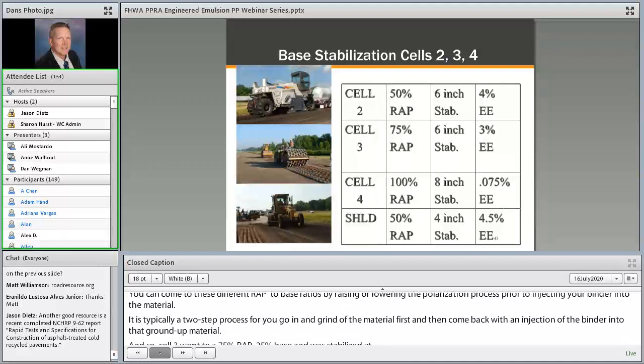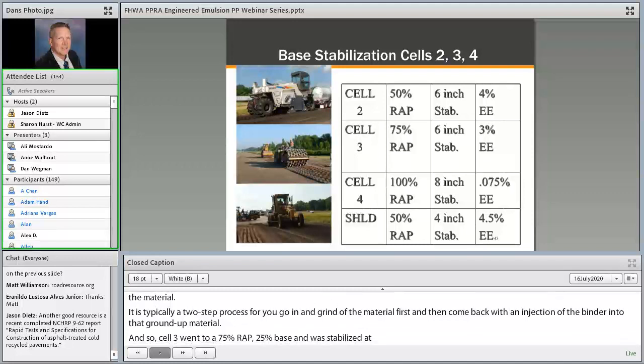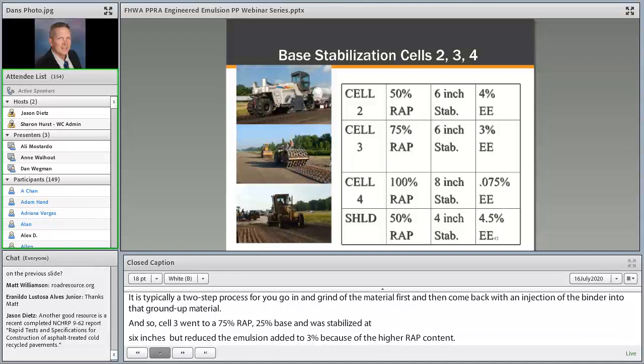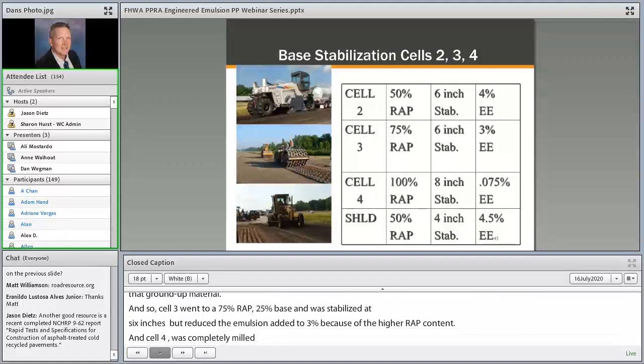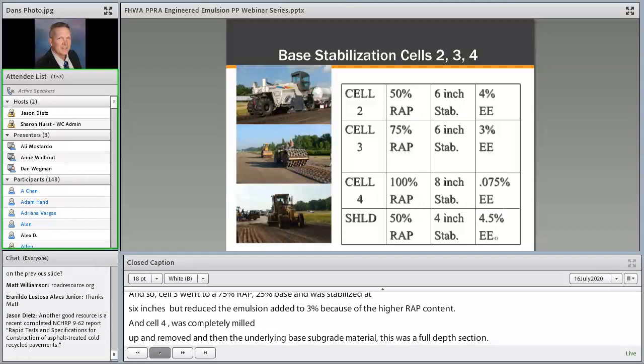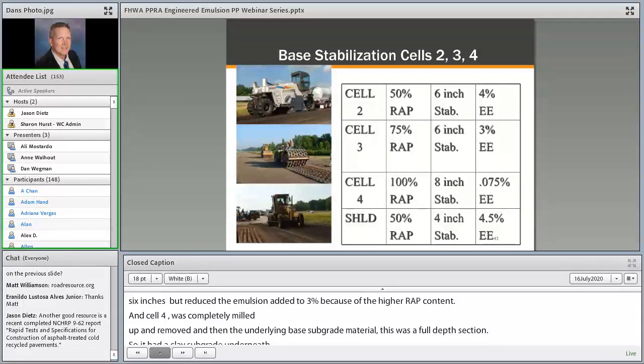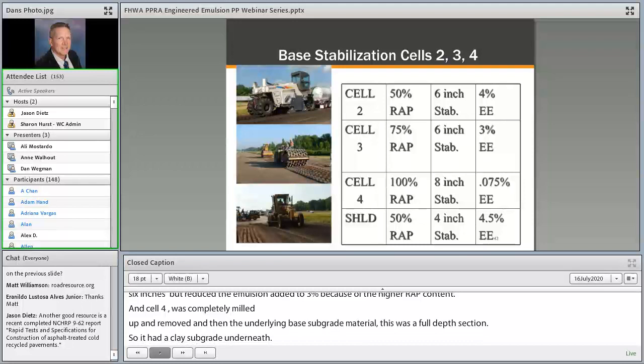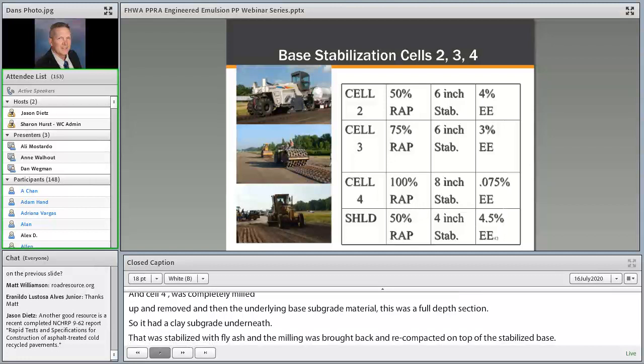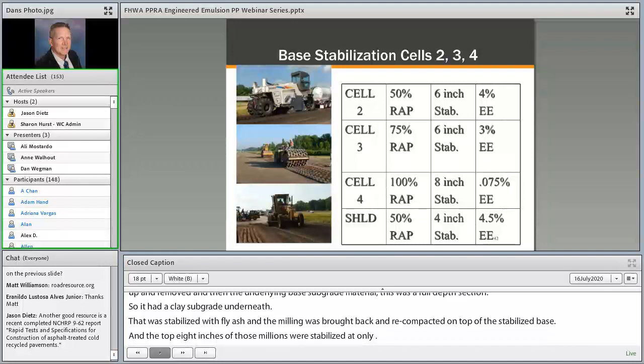And then cell 4 was completely milled up and removed, and then the underlying base subgrade material, this was a full depth section, so it had a clay subgrade underneath. That was stabilized with fly ash, and then the millings were brought back and recompacted on top of that stabilized base, and the top 8 inches of those millings were stabilized at only 0.075% emulsion, so you can see that much less emulsion was used in this 100% RAP stabilized material.